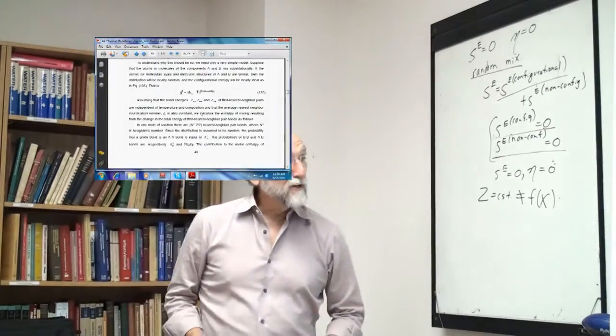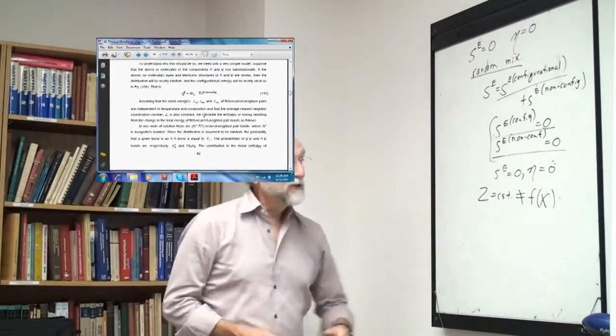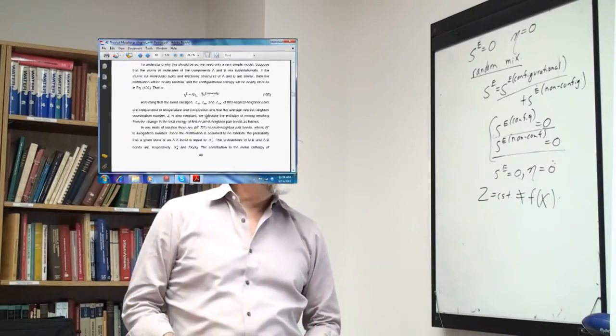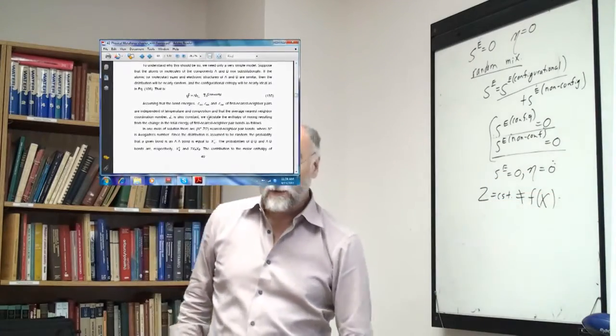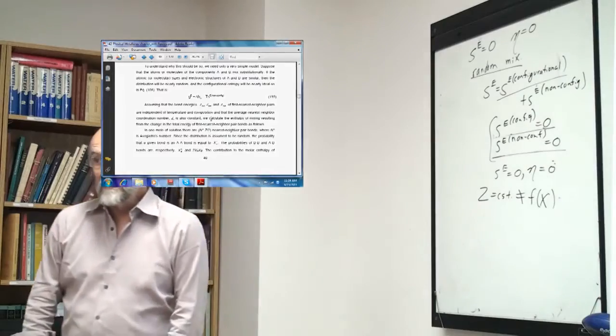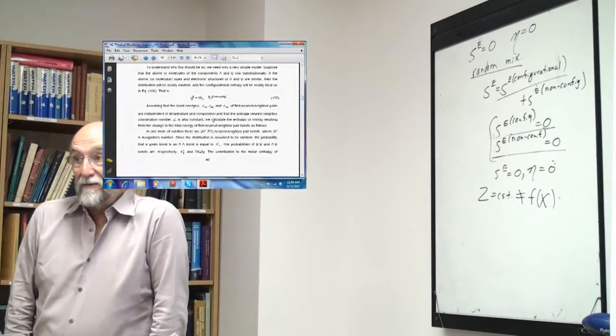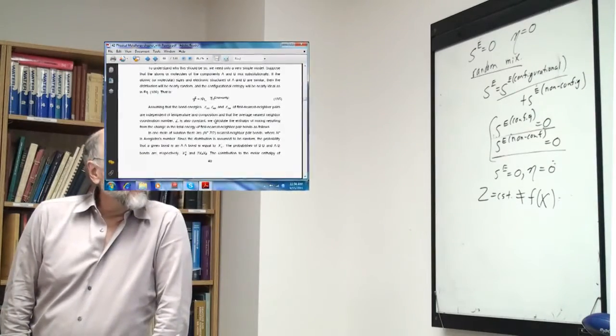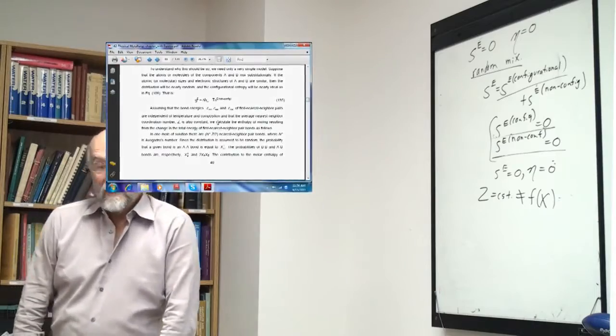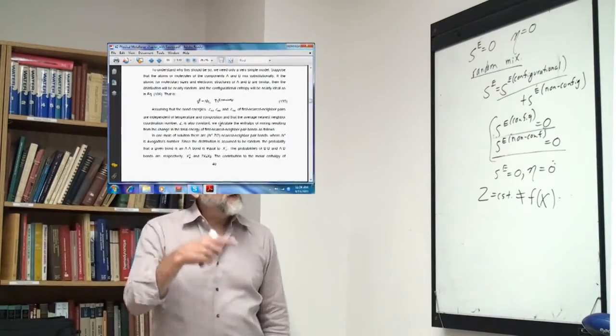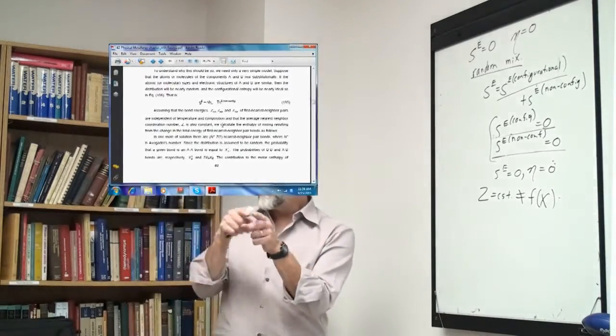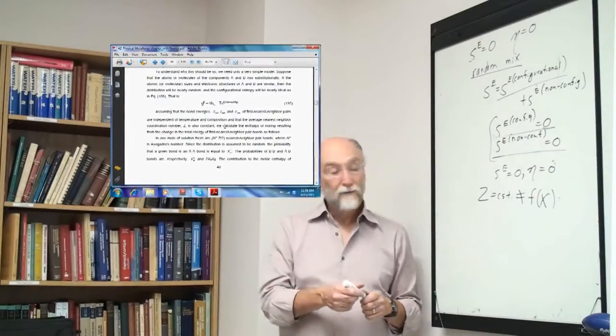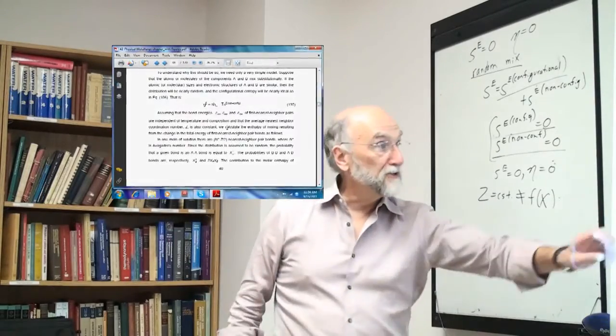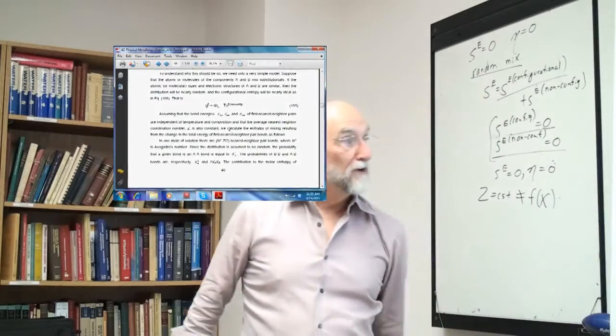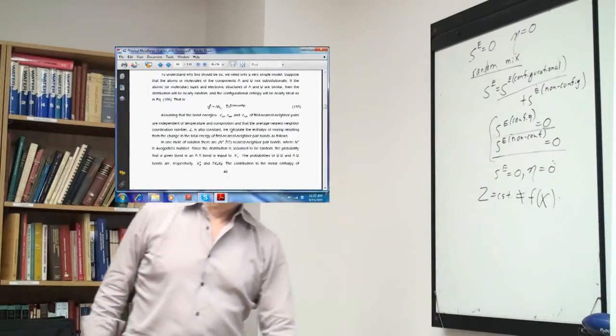So how many nearest neighbor bonds are there in 1 mole of solution? Well, there's N0 Z over 2 nearest neighbor bonds, where N0 is Avogadro's number. So the number of atoms is N0, Avogadro's number. Each atom is surrounded by Z nearest neighbors. And if you have N0 Z, you have to divide by 2, because otherwise you've counted every atom as a central atom. So N0 Z over 2 is the total number of first nearest neighbor pair bonds in the solution.